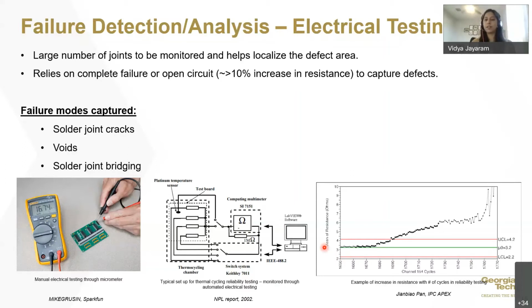So you would have some expected resistance, and with more accelerated stress testing, you would see the resistance going up, and you can have different variations of how the resistance goes up. For almost a brittle failure, you would have the resistance rise up immediately, as opposed to a fatigue induced failure, for example, like thermal cycling, where you would see the resistance go up gradually over time and then cross a particular threshold to be detected.